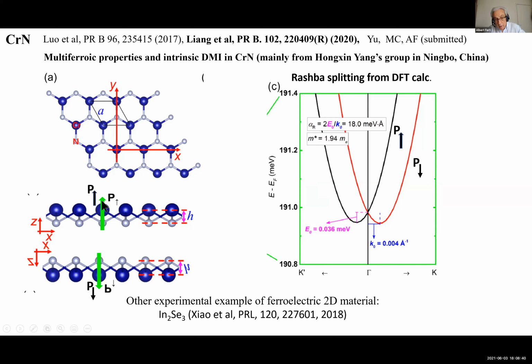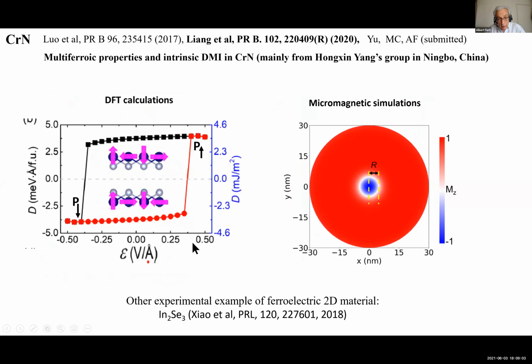by switching with an electric field, with a gate electrode, between these two configurations. Generally the Rashba effect goes with the Dzyaloshinskii-Moriya interaction, and there is a simple relation between the Rashba constant and the DMI. Of course, this has been verified by DFT calculation, starting from this ferroelectric polarization and applying an electric gate voltage, one switches the system to the up electric polarization, and at the same time one goes to a Dzyaloshinskii-Moriya interaction of different chirality.